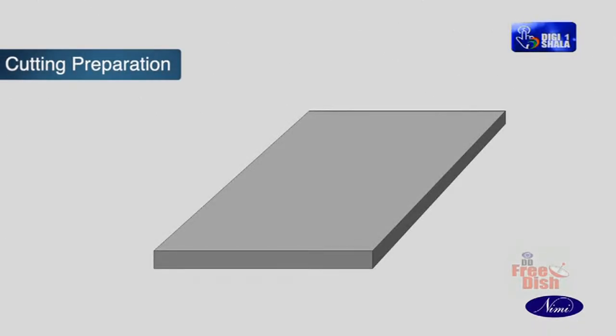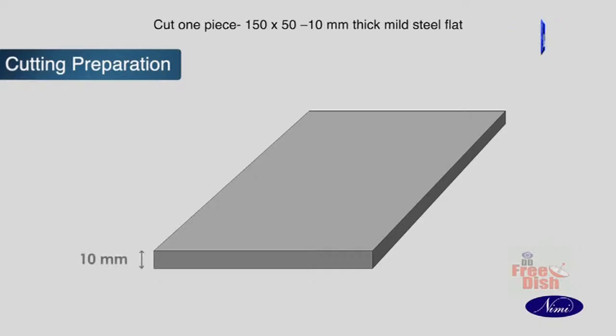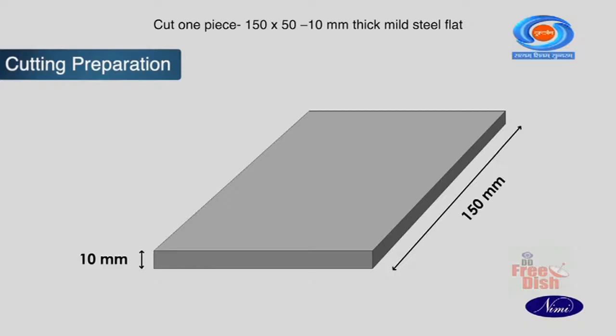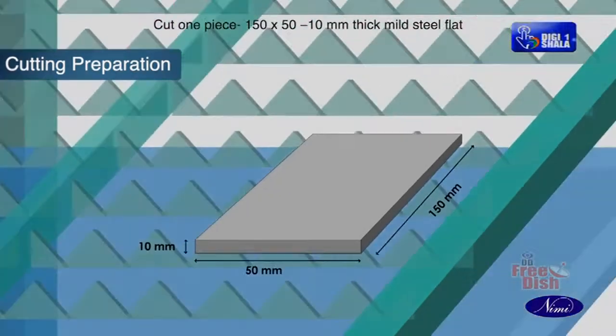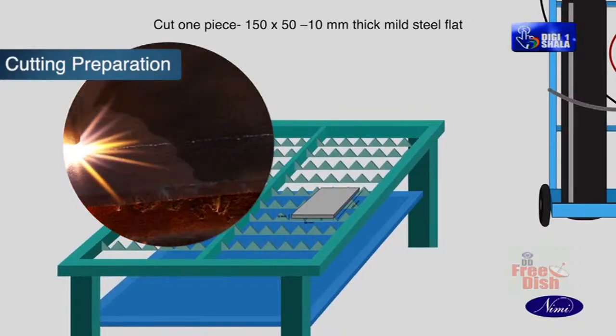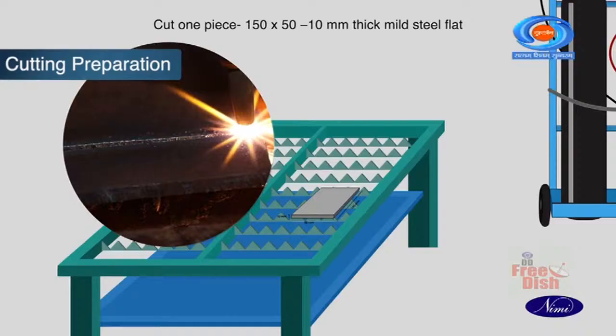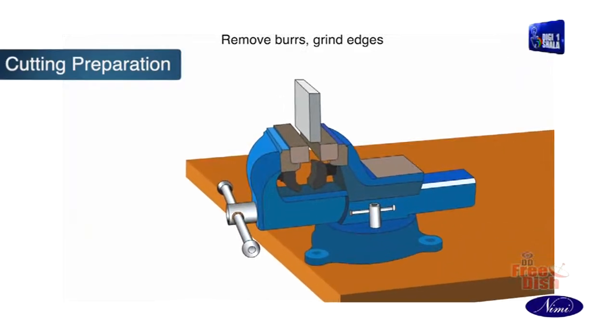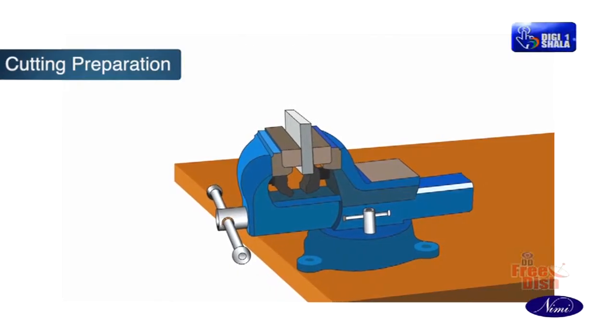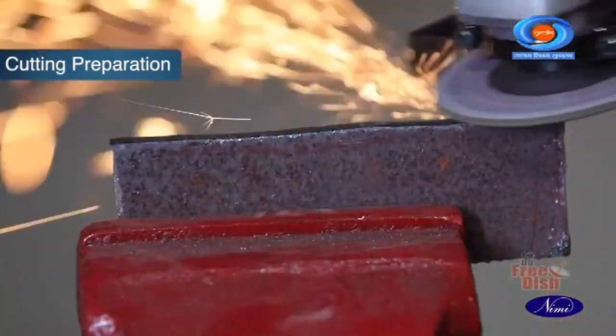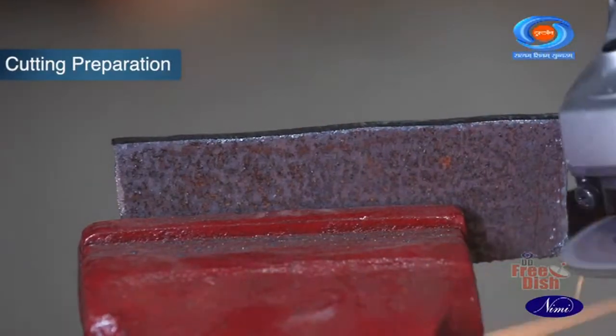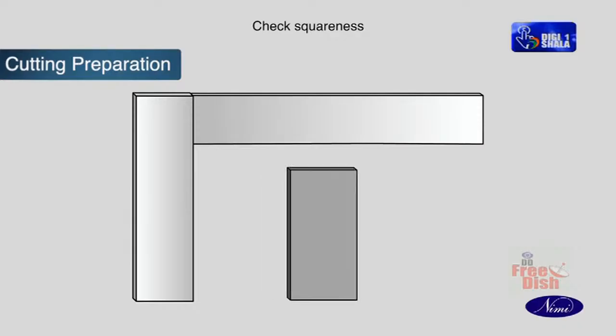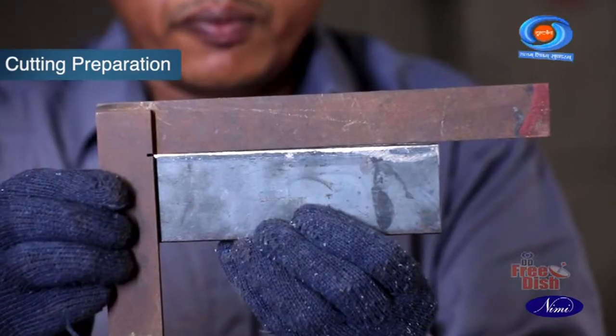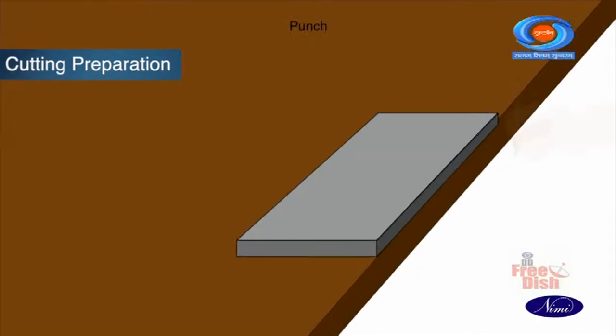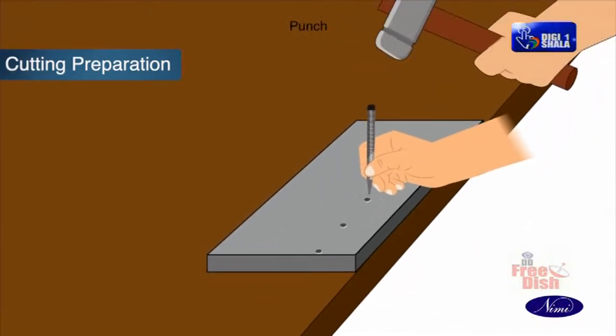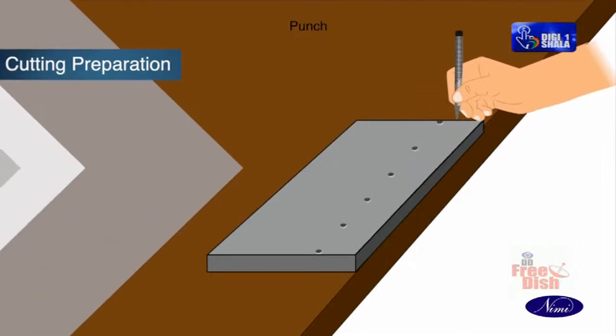Let us see the preparation for the practical. Cut a piece of 10 mm mild steel flat. Remove burrs, if any, by fixing it on a vise. Check for the squareness of the MS plate. Punch along the straight line for gas cutting using a prick punch tool.